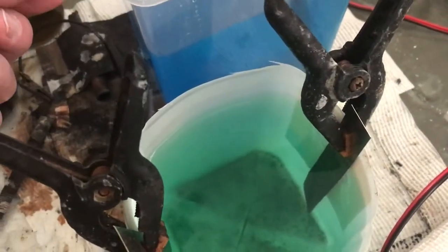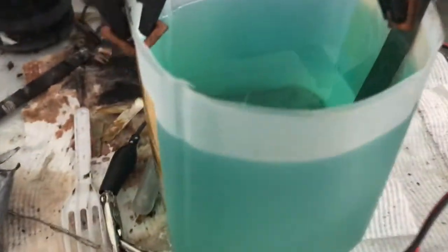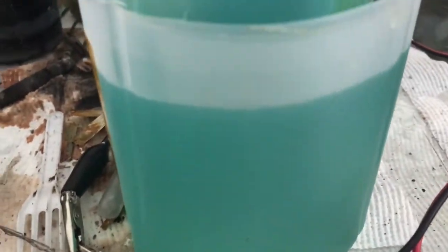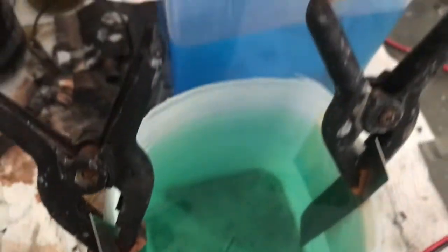The nickel acetate's ready. It took 6 hours at 4 volts and about 500 milliamps to get this stuff done. I think there's some zinc floating around, nickel floating around the bottom. So I'm going to attempt to nickel plate this now.